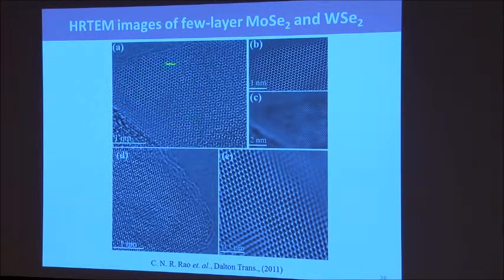We can analyze these electron microscope pictures very nicely. Here is tungsten selenide, a single-layer tungsten selenide, a high resolution microscope picture of that. So we can study all this microscopy, structure, and a number of properties of this single or two-layer sulfide, just like we did in the case of graphene, and that has been done.